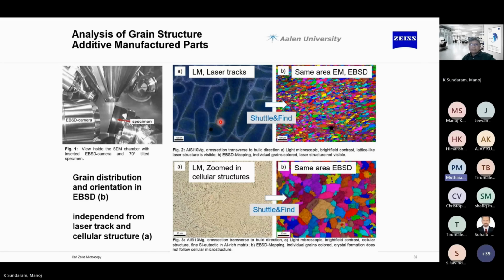And this is one technique used in the electron microscope. We call it EBSD, electron backscatter diffraction technique. How it helps is, it will identify or help you understand the lattice pattern of the grain structure during the printing process and the heat treatment cycle, whether these printed materials are properly formed during the heat treatment process, whether the orientation of the grain formation is happening in the same direction so that the required tensile strength is being achieved or not. So this is one accessory attached to an SEM, whereby you are able to get this kind of grain pattern or lattice information. Next slide, please.